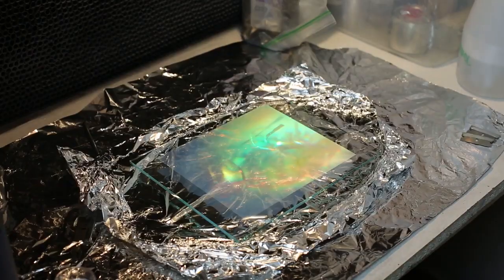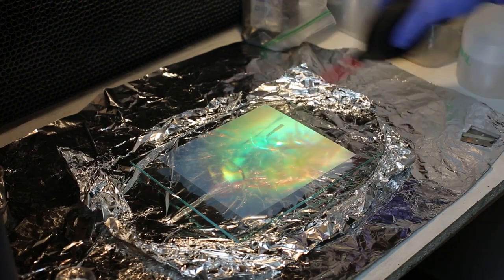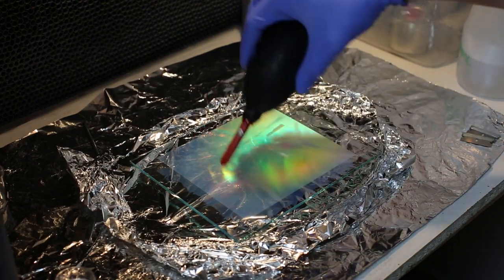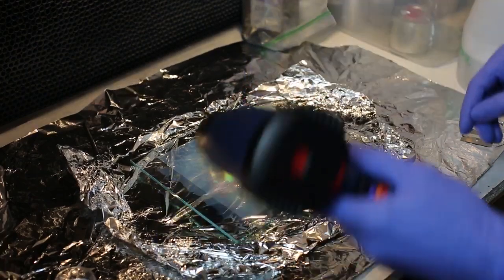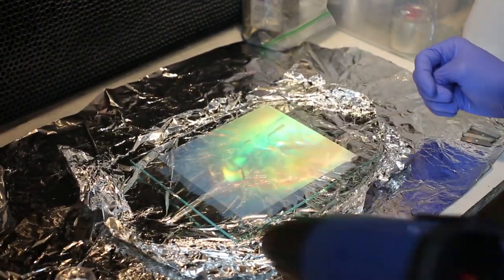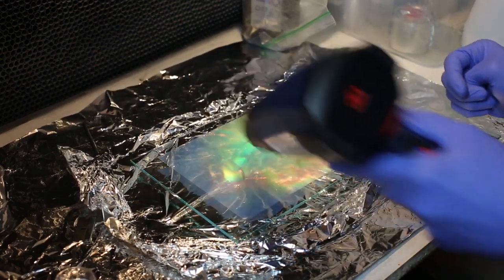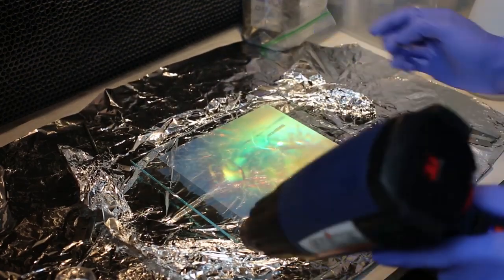With the photographer's lensed dust blower, I blow any possible dust off the hologram. With the heat gun set to the low setting, I blow over the plate and warm it up. Warm glass bonds much better with the epoxy glue. Next, I have to choose a piece of glass that will cover the plate. This cover plate should be 3 centimeters bigger on all sides than the hologram you want to seal. There should be some overlap as a safety margin when gluing 2 pieces of glass together.